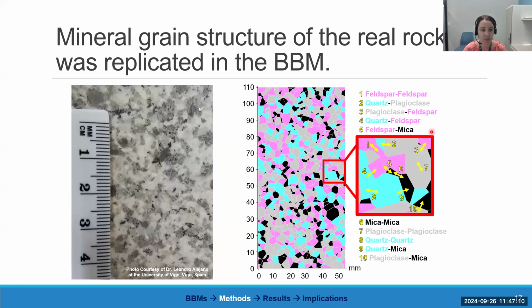So they all do have cohesion, and residual cohesion goes to 0. So I think it ranges between maybe 2 or 3 to maybe 35 megapascals for the peak cohesion. So once the strength of the contacts is reached based on the cohesion and the friction angle, then it degrades to residual values, where I believe the residual cohesions were all 0, and I believe the residual friction angles were about 5 degrees for the contacts, whereas the peak friction angles ranged from, you're testing my memory here, it's been a couple years since the PhD, I think about 20 to 50 degrees, depending. So like a quartz-quartz contact, for example, will be very strong, whereas a mica-mica contact will be soft.